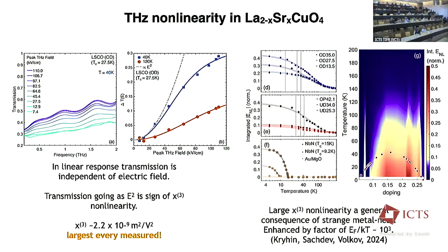Do I have to worry about that here? Can one tune this sort of bottleneck about how quickly the photon will break? Yeah, it's a good question. We've done work, which I didn't present; the first material we spent a lot of time working on was strontium ruthenate. It's not very apparent in the cuprate data, but in strontium ruthenate there's a really long time signal that looks very similar to this, but doesn't completely go back to where it was on the scale of 10 or 20 picoseconds. It seemed to persist for the longest time that we had. What we argued in that paper was that this was a very long time scale associated with diffusion of heat out of the film altogether. They're thin films, so I think they're reasonably well coupled to the environment. Is this very important for the kinds of statements we're making here? I think it's probably not.